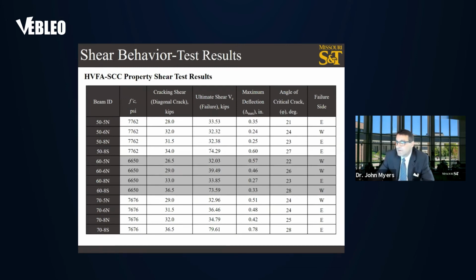Following the test results, the test data was summarized in this table for the 50% fly ash, 60%, and 70% fly ash. As you can see here, all of the tested beams failed in shear. In general, there was no major difference in the cracking and ultimate shear forces for the same reinforcement details, with the increase of cement replacement levels.